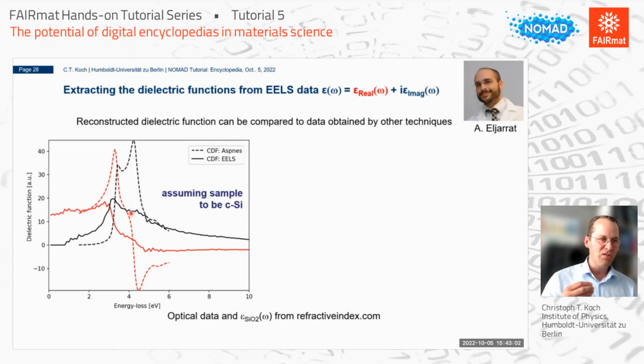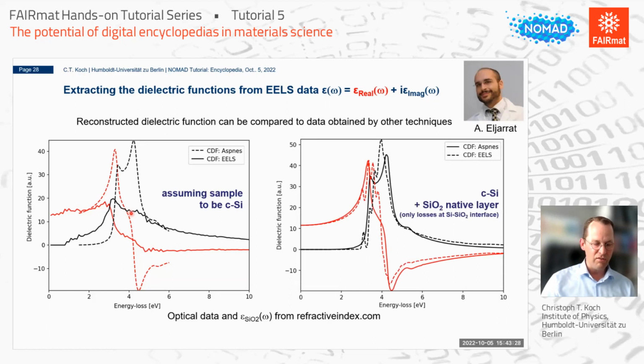But if you now know something about your sample, and that is information that one really needs to invest in recovering: silicon grows a native oxide if you expose it to air. If you assume there is also a silicon dioxide silicon interface and include that in reconstructing the dielectric function from your experimental data, then the agreement between the EELS-derived dielectric function and the optical dielectric function gets much better.